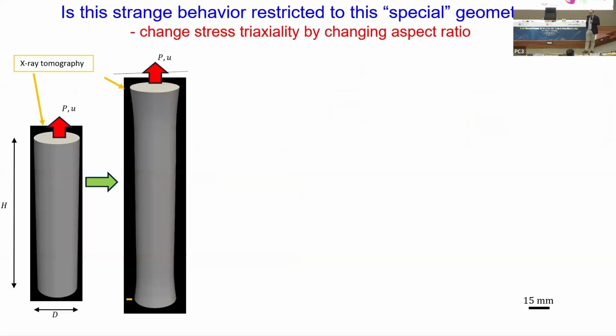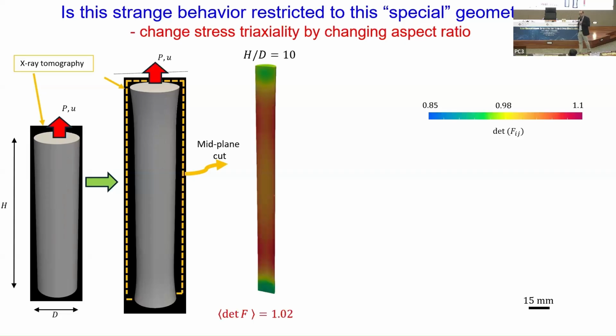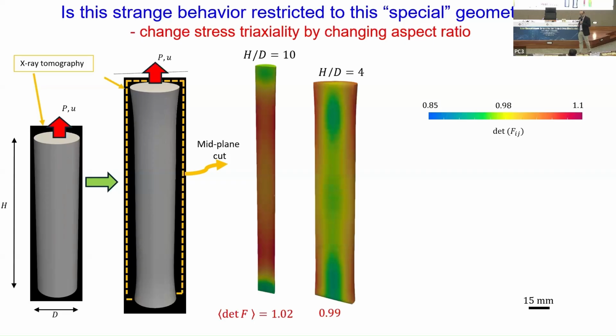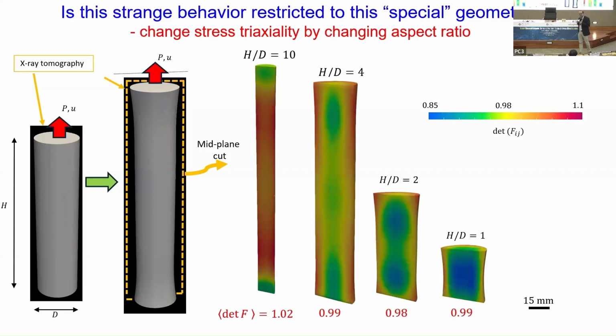Okay, so what is the problem? Is this strange behavior related to this specimen geometry, or is it something else that's happening here? So we made specimens of different aspect ratios. This is a very long specimen. This is a shorter specimen. This is a shorter specimen. And this is the shortest specimen that you were seeing.